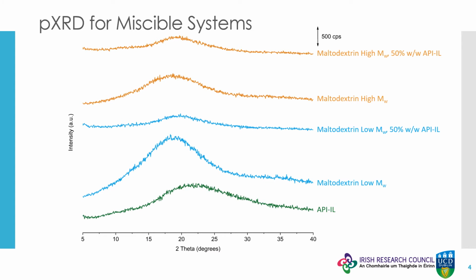Powder X-ray diffraction was used to verify that the material produced conserves the liquid form of the API as amorphous materials. The diffractograms presented here show this to be true for both grades of maltodextrin by the diffuse halo patterns and absence of Bragg peaks.